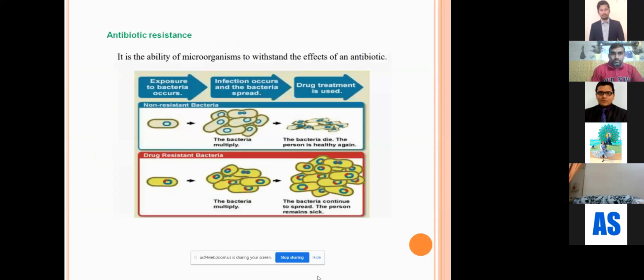Now, why do we want to functionalize these nanoparticles? Today, the world is suffering from a lot of bacterial disorders, and basically we are suffering from multi-drug resistance because of the phenomena of the bacteria. They are continuously creating illness in human cells, and they keep on multiplying when they get resistant to the antibiotics. So functionalization in terms of nanomaterial, particularly with the magnetic nanoparticle, has a lot of reports and publications already published. We have also published while working with magnetic nanoparticles for bacteria, and we could see that quaternary ammonium compounds, which I will show in my further slides, are able to control the biofilm formation of the bacteria.